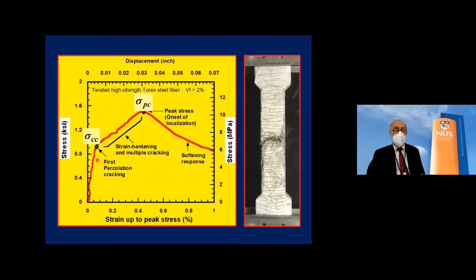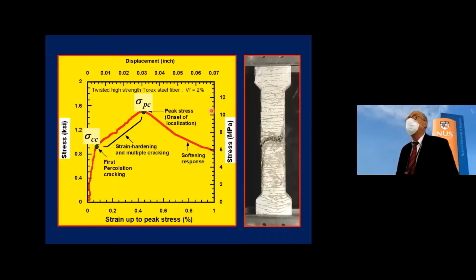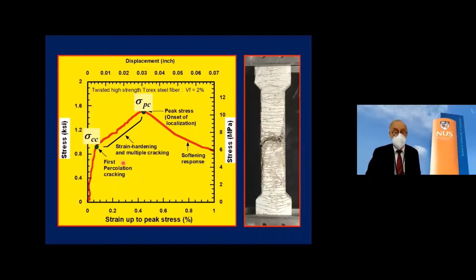You could see clearly first cracking, maximum post-cracking stress. The specimen has been sprayed here with alcohol so we can take a good picture of where the cracks are. And 10 megapascal in direct tension and sufficient ductility is a very, very good response. But this is a real specimen.